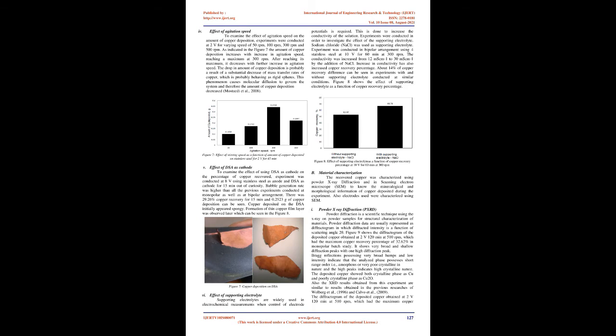In the second set, using bipolar batch arrangement, experiments were carried out at 5V, 10V, and 15V. The maximum copper recovery of 56.99% was observed at an applied voltage of 10V, and recovered copper is shown in Fig 2b. For 15V, copper deposited in the initial stage but appeared black after 2 minutes, and the color of the wastewater completely changed to green. The results are illustrated in Table 4.